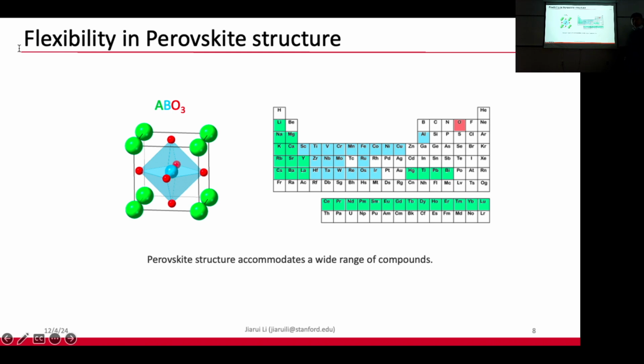So Jiarui, how are you defining a perovskite structure here? That's an FCC with an addition in the middle? Yes, but the red atoms are oxygen, so the basic structure is still cubic. You can see that the main structural framework is the corner-sharing oxygen octahedra network connecting up, down, front, back, and left, right. Yeah, it's normally cubic, but the flexibility of this structure helps.